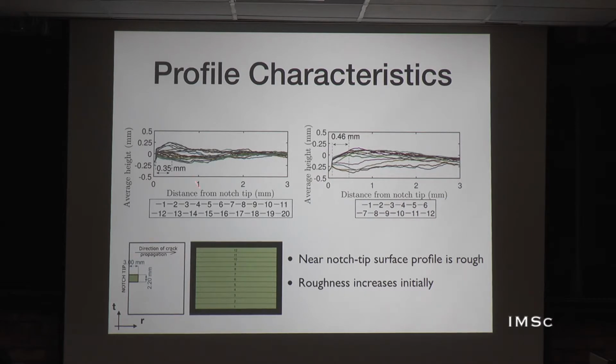And we observe very interesting features, that we do see that slip plane crack that people were, okay, I will come to that later. Looking only at the surface profile, we see an increase in the deviation in the surface profile up to a point. Beyond that, it slowly comes back to a very smooth profile with not much scatter in the height. Exactly the same way here, the notch tip is here, and it's going upward and downward. Up to a point, it is going away from mode 1, where the remote load is tensile and the plane opening stresses are maximum along the 0 degree. But we are seeing these formations which go up to a point and then come back.